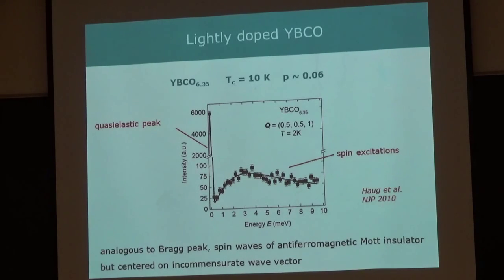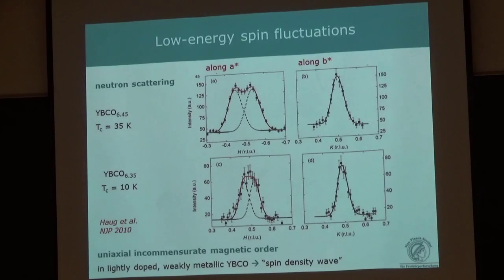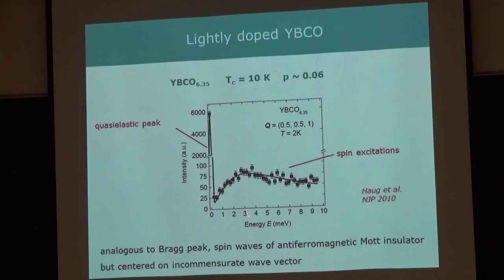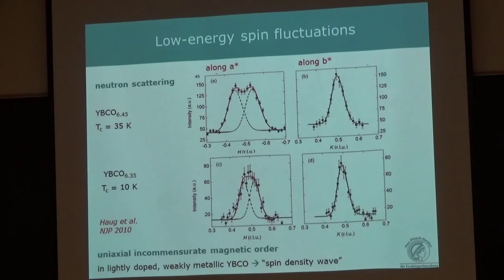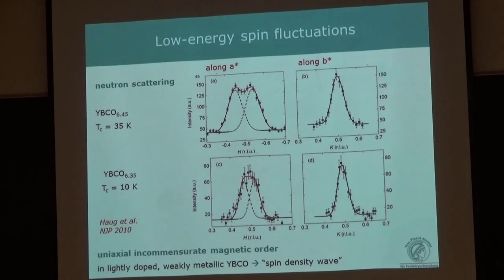The finite doping is reflected in a small shift from the commensurate position. Looking at the inelastic scattering spectrum, you're cutting across this magnon-like excitation and you see the spectrum becomes broader and splits in the A-axis direction, whereas the signal remains commensurate in the B-axis direction. This means the modulation in lightly-doped materials is actually uniaxial. H and K are the momentum coordinates in the copper oxide layer. You can write the momentum transfer Q in the two in-plane coordinates within the copper oxide layers.